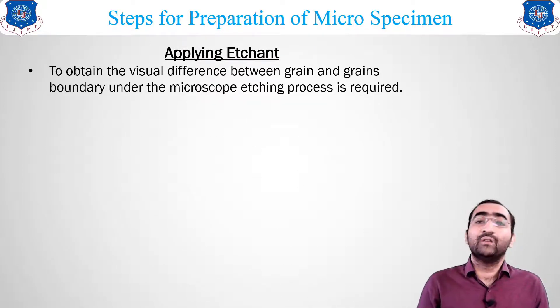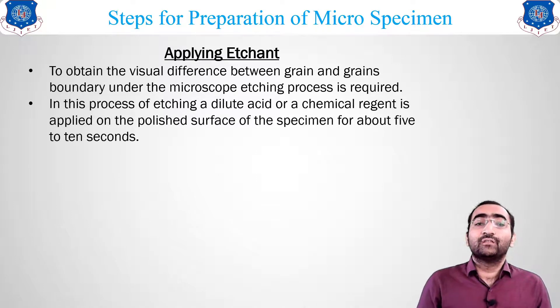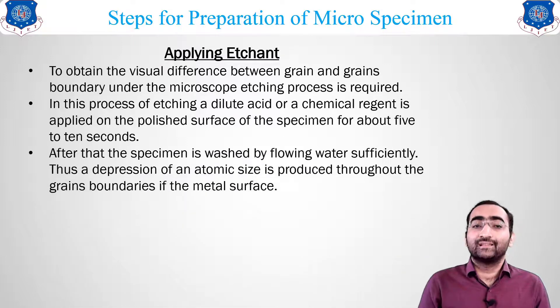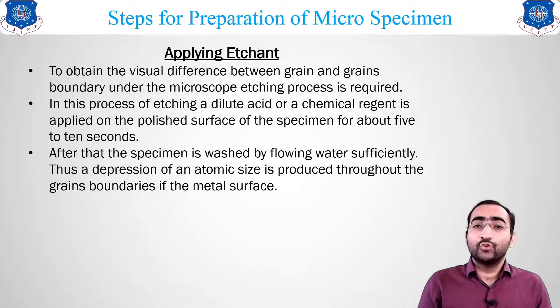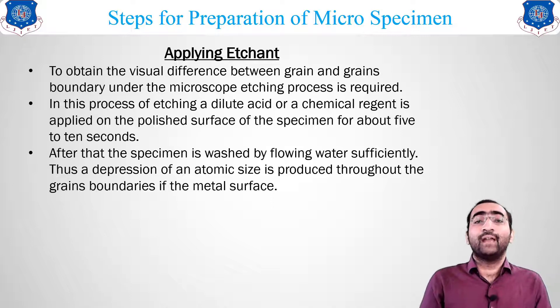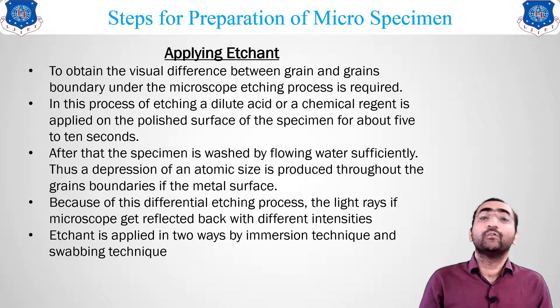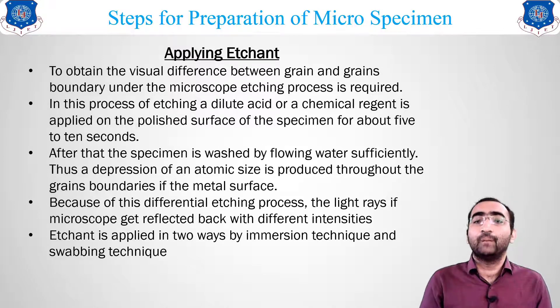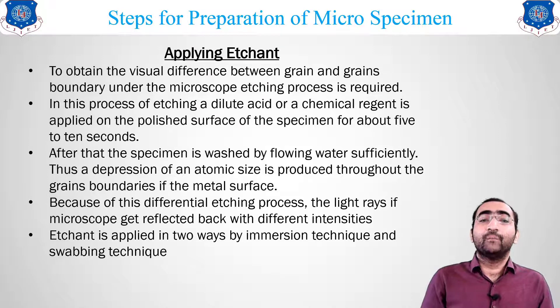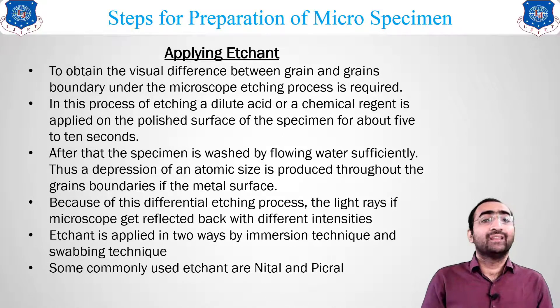The seventh step is applying etchant. To visualize the difference between grains and grain boundaries under the microscope, etchant — a type of acid — is applied on the polished surface for about five to ten seconds. The specimen is then washed and taken directly to the microscope. Etchant also differentiates between two metals in an alloy. Without etching, everything appears the same. Methods of application include immersion, swabbing, or spraying. The commonly used etchants are Nital and Picral.